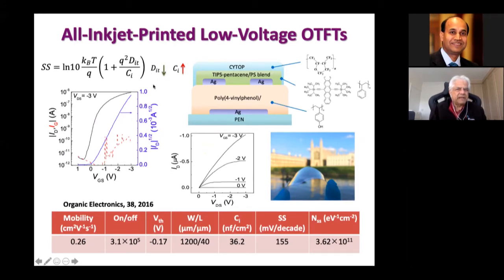the interface state density. So when fabricating this, this was on a PEN substrate, with a silver printed gate electrode. The whole structure was printed by that printer that I just showed, and was encapsulated by Cytop. The active channel region was a TIPS pentacene polystyrene blend. And the key was getting the process steps right for this interface with the dielectric. This is a PVP dielectric. And by careful control of that interface, we managed to bring DIT down to very small values.